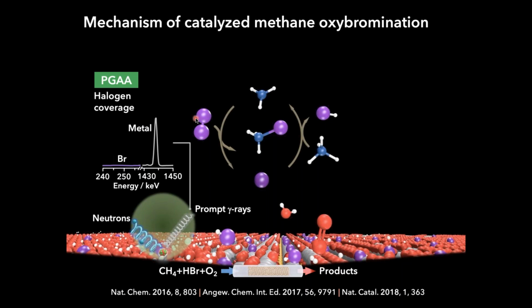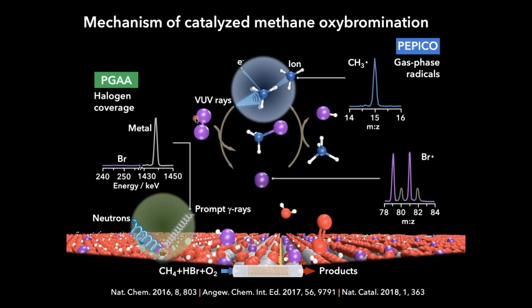For that to be proven, we need to verify that we have bromine and methyl radicals in the gas phase. And for that, we need another technique that is sensitive to gas phase radicals. And this is PEPICO, photoelectron photoion coincidence spectroscopy, using vacuum ultraviolet light again to excite the gas phase species and to get the mass spectra to prove their absence or existence under reaction conditions. This was done in operando mode, at the same time as the reaction was happening under operating temperature conditions. And what we could see is that with this tool, we were able to indeed monitor methyl radicals in the gas phase and bromine radicals in the gas phase, as well as molecular bromine, what you see here in gray. So that verified our mechanism.